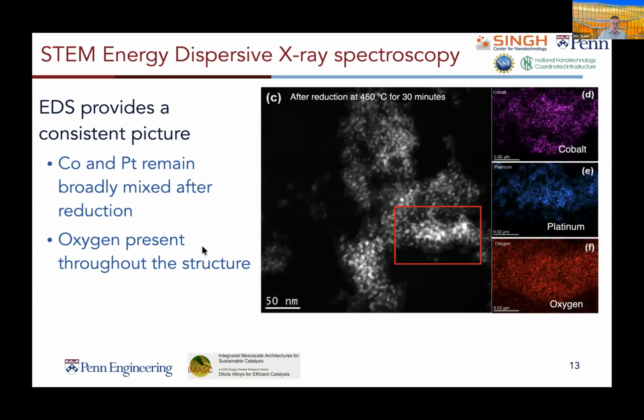If we want, we can also do energy dispersive X-ray spectroscopy. We again see that in this case, after reduction, the cobalt and platinum remain broadly mixed, and there's oxygen present throughout the entire structure.